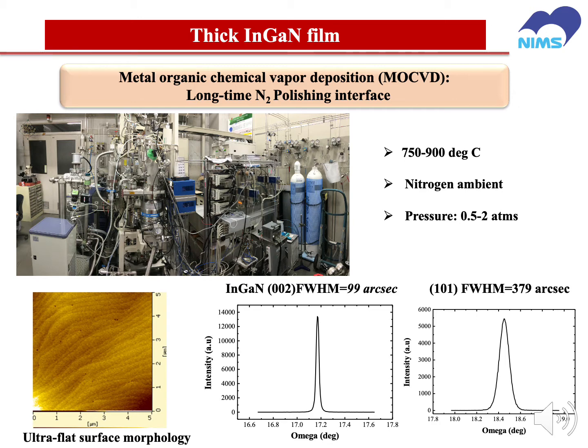To improve the interface morphology between the indium gallium nitride and the gallium nitride, we introduced a very special long-time nitrogen polishing method. Another modification is that our MOCVD system has high-pressure growth conditions, because at high pressure we can obtain very good quality indium gallium nitride film at a relatively higher growth temperature. This is our specially designed high-pressure MOCVD, which can theoretically go up to 3 atmospheres, which is unique compared to other MOCVD systems.